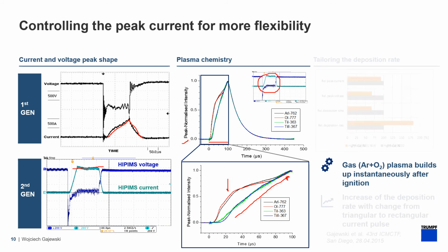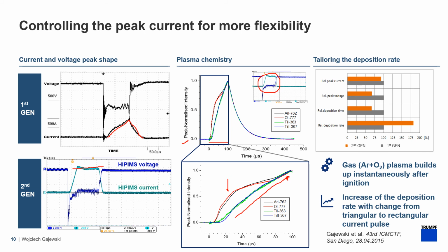This is one advantage. The second one is the possibility to tailor the deposition rate. And already in 2014-2015, with the second generation of these power supplies with rectangular shape of the current, we were able to show that it dramatically increases the deposition rate, by a factor of almost 2. And this is the very important advantage of changing the shape of the HIPIMS pulse.